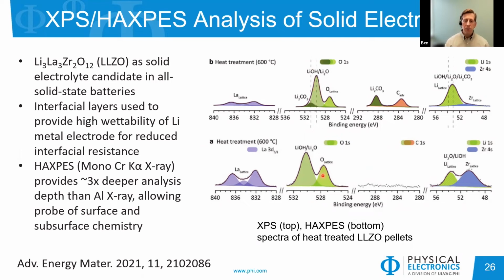But if we look at this with HAXPES, we're looking a little bit deeper into it. We do see more of an oxygen signal from the LLZO lattice, similar to the zirconium signal. We see a higher relative percentage of zirconium with the HAXPES compared to with XPS. So with that, we can understand that the lithium hydroxide type species tend to be more toward the surface, and we're looking a little bit below that with the HAXPES. So it's a non-destructive way of looking at different information depths and still seeing some different chemistries.